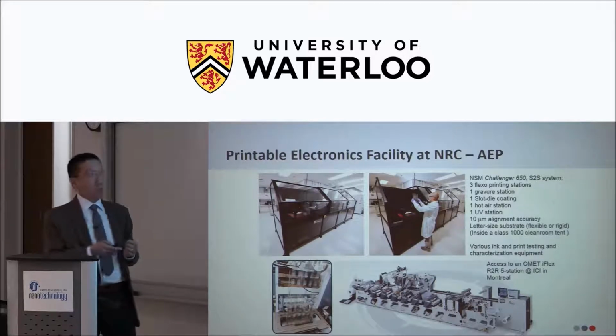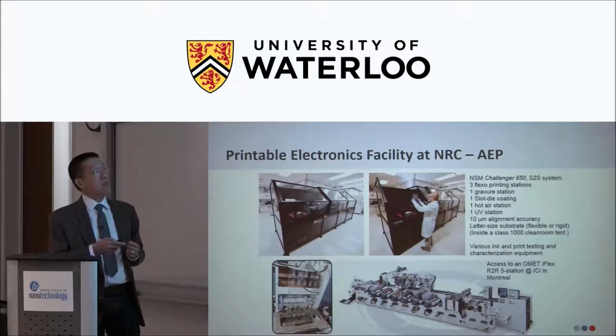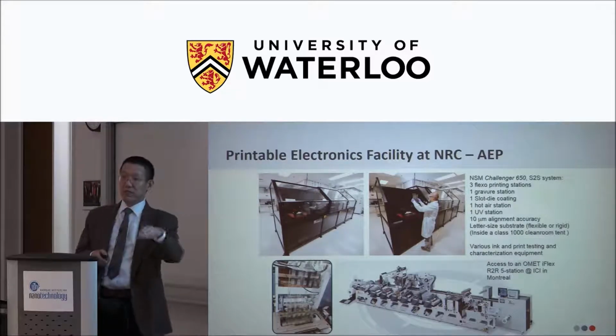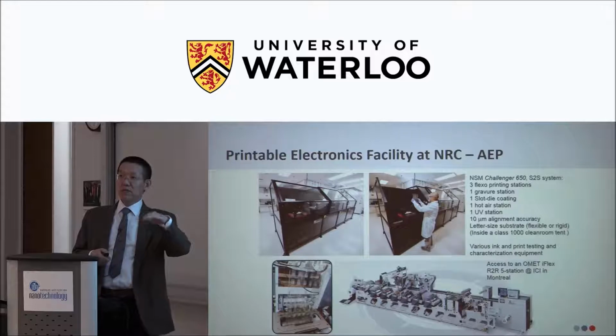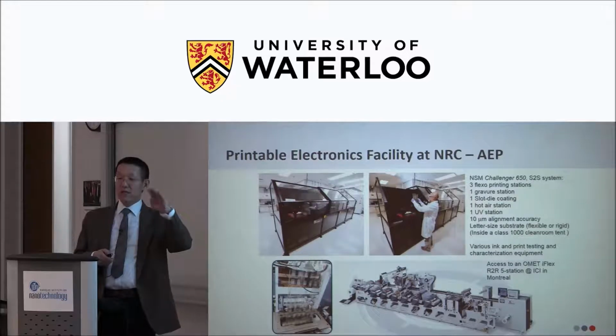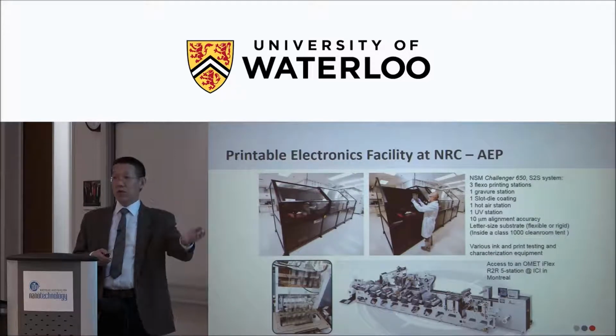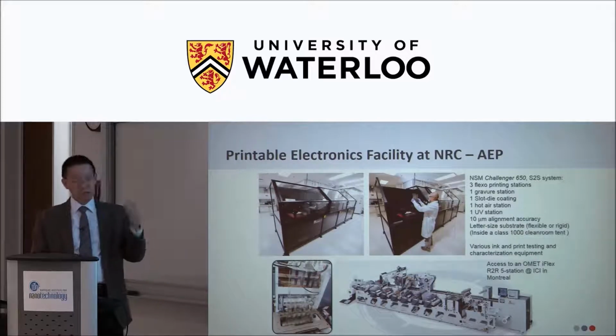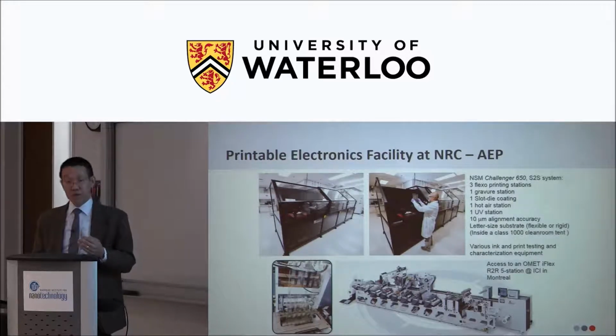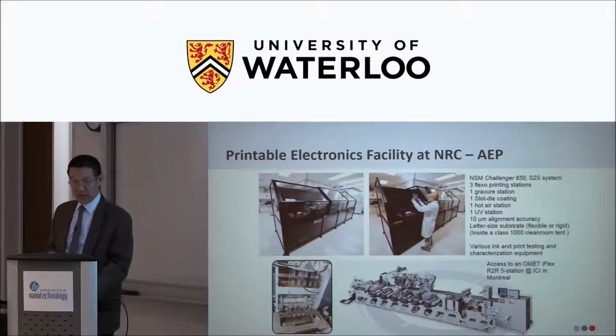So in our case, the sample is movable from station to station, and we can use the curing station or drying station. You can control temperature, high and low. You can have a different dwell time for device fabrication. So it's actually very ideal for making multi-layer semiconductor devices.